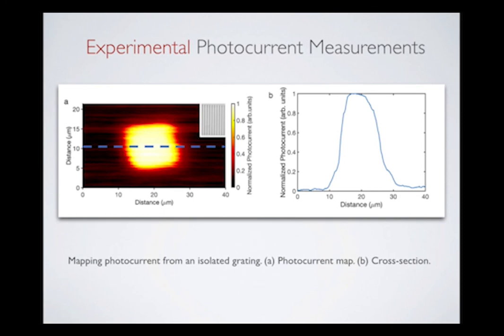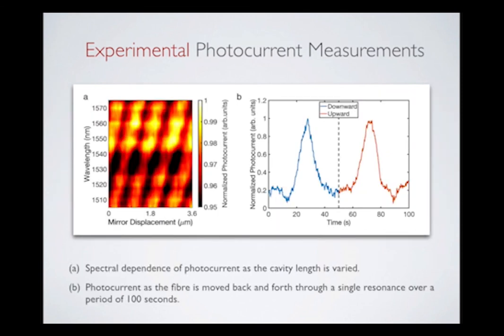Initially, the photocurrent was mapped from an isolated grating, i.e. without a cavity, in order to confirm the plasmonic origin of response. The output from an uncoated cleaved fiber was scanned across the grating, with the resulting current recorded for each position. A clear hotspot with dimensions close to the milled grating is evident in the current map with the cross-section shown in Figure B. Once SPP-induced photocurrent was demonstrated, the second mirror, formed from the cleaved fiber coated in a 10 nanometer thin gold film, was put in place and scanned in the Z direction in order to elucidate the influence of optical cavity modes.